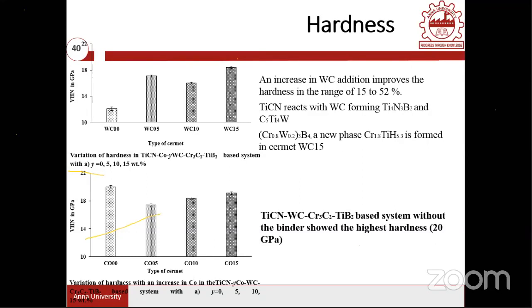But we have to have a combination of good hardness as well as toughness. Therefore, we cannot recommend this combination as a tool material, whereas we can recommend other compositions as a tool material. If you look at CO15, you have a really nice value, 19 GPa obtained. So we have seen here what is the role of every addition.